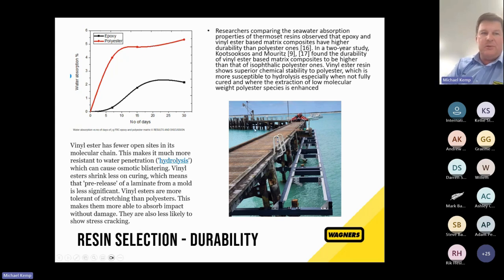So if we're talking about marine piles or even in the vicinity of marine applications, so either in the water or certainly exposed to the water, we definitely have seen, and there's a lot of data now on the performance of vinylester over polyester. It does come down to a fair bit of chemistry as well. We're seeing that because of their superior chemical stability, and also their tolerance of stretching, or their elongation to failure, as we were just talking about, we're not getting that micro cracking in the matrix, and we haven't got that avenue for the onset of moisture absorption and therefore durability issues.